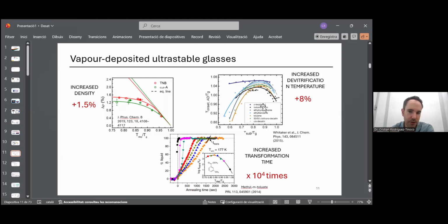This is what I was saying before: the onset temperature of the devitrification as a function of the deposition temperature. We have here many materials. Nowadays, we have many more materials than this. There are many materials that follow the same trend. The onset of the devitrification when we heat from the glass to the liquid is maximum when the glass is deposited around 85% of the glass transition temperature, which is around this value here. And these glasses are called ultrastable glasses because of the larger thermodynamic and kinetic stability, but also because when we take this glass and go above Tg, above the glass transition temperature, it takes much time to transform back to the metastable equilibrium state, to the liquid state.